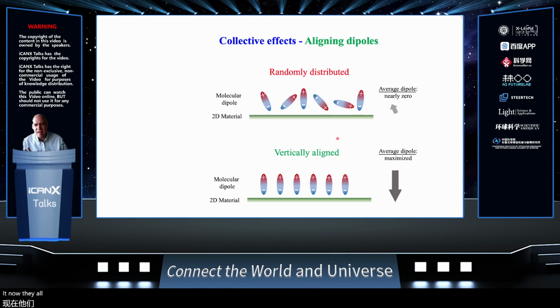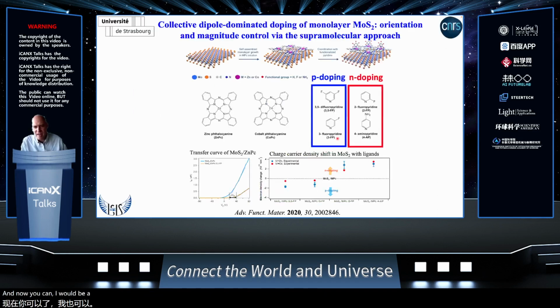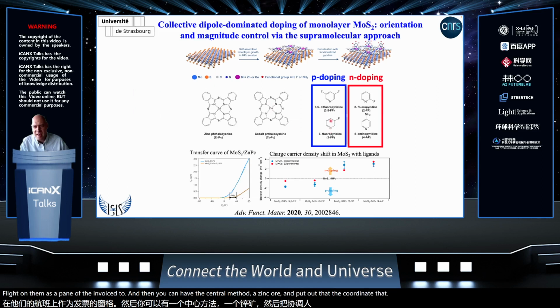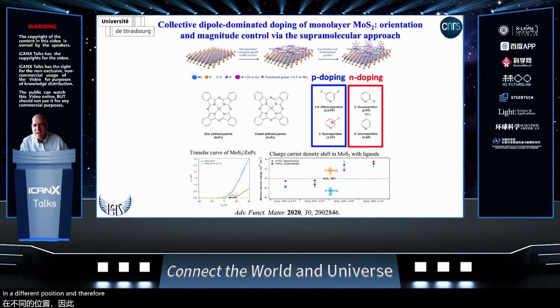Now, the whole idea here is that if you want to maximize this kind of doping effect, you have to be able to control dipoles and align all of them in order to take advantage of this collective effect. I will be quite brief because time is flying. Since a key is the orientation of the dipole perpendicular to the basal plane of the surface, you can use a coordination chemistry approach. You can physisorb a metal phthalocyanine flat on the basal plane of the MoS2, and then the central metal, zinc or cobalt, coordinates the pyridine unit. The pyridine can be functionalized with a fluorine atom in a different position, and therefore we can control the orientation of the dipole moment.